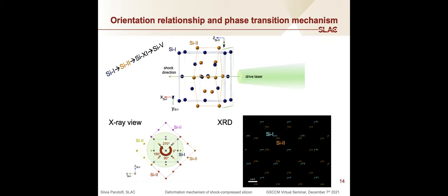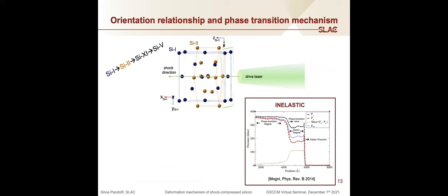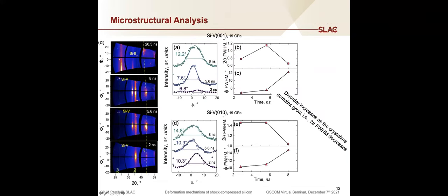So we actually have a sort of phase transition pressure that basically gives us the shear release. In this sense, it's inelastic, meaning that it doesn't involve the generation of defects, but it's only caused by the phase transition itself. It's the geometry of the phase transition that dictates the equilibration and the relaxation towards a hydrostatic state. We think this is pretty nicely visible in our data, because we see that the nucleation of the high pressure phase happens with very strong preferred orientation.